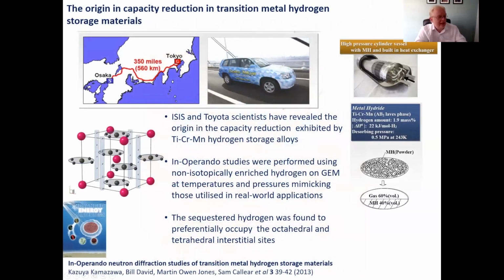Okay, so an example of some of the diffraction studies that we've done, this is one that we did with Toyota quite a few years ago now. Toyota originally wanted to put the hydrogen for their hydrogen-powered cars into tanks that contain transition metal alloys. The reason they wanted to do that is because there's a volume saving on the tank size. But what they found was they had this proprietary titanium, chromium, manganese hydrogen alloy, and when they put their hydrogen in, they only got about half of the hydrogen back out, and they wanted to know why that hydrogen wasn't coming out. And so we did a neutron diffraction experiment on this.